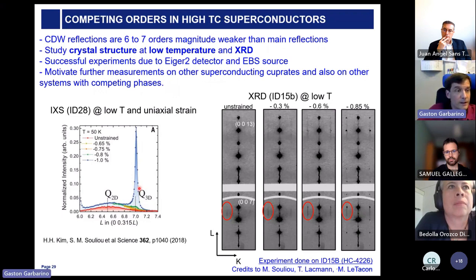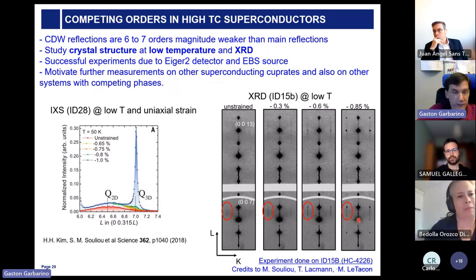So the idea is we are really able to apply uniaxial pressure on your sample and follow the appearance of these charge density wave peaks that are 7 orders of magnitude lower in intensity with respect to the mean Bragg intensity of the structure, meaning that we now have the possibility to develop this type of study.